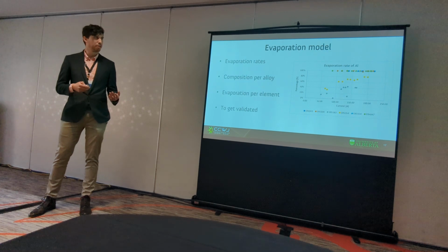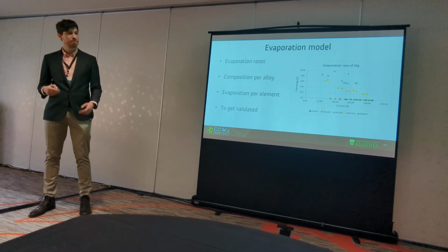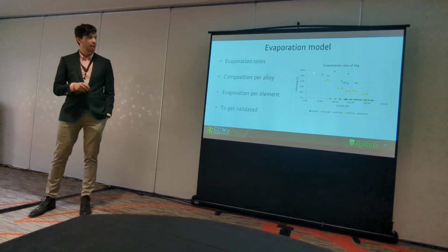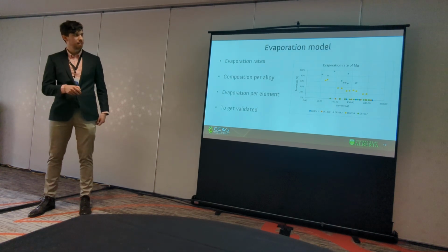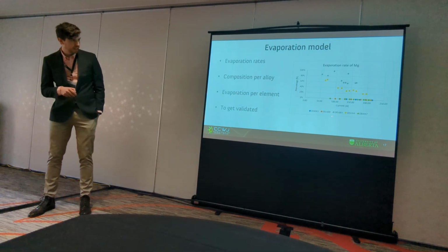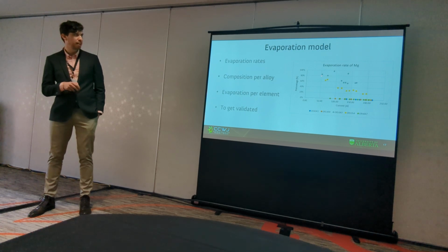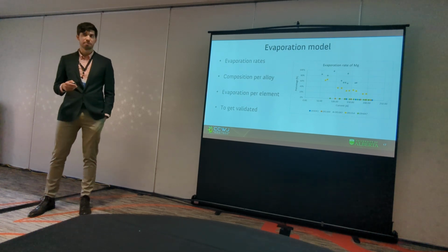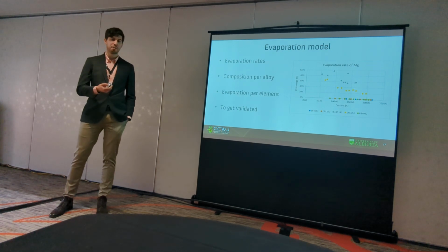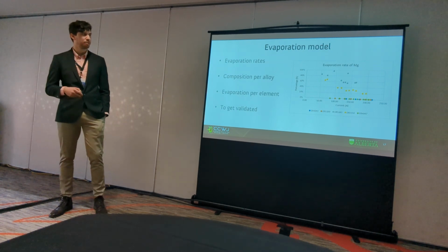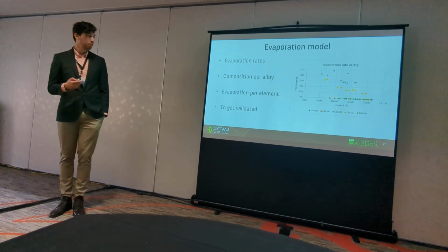So what is the rest? Well, it can be magnesium in this case. So we see how the magnesium evaporates at the beginning. For 5183, almost all of the gases can be magnesium, which is quite a lot. If we put magnesium in this alloy, we don't want to lose it and throw it into the air. So it's good to see that somehow we are, or we could.